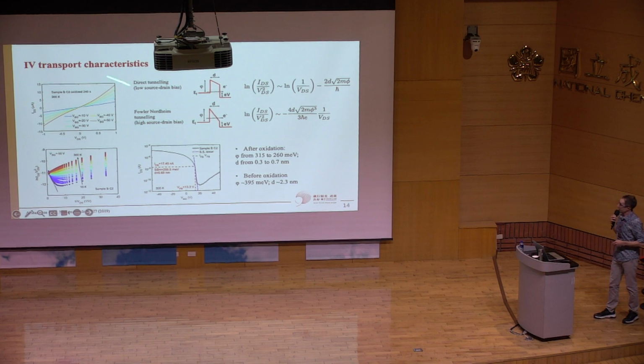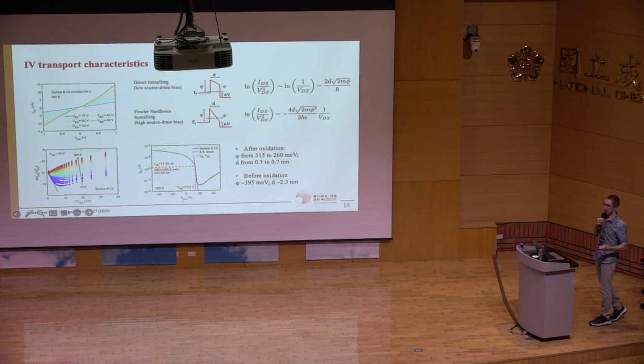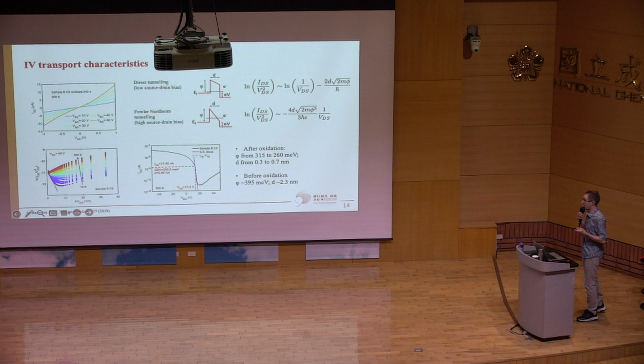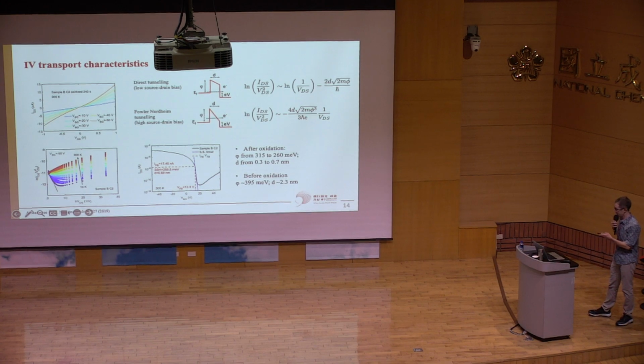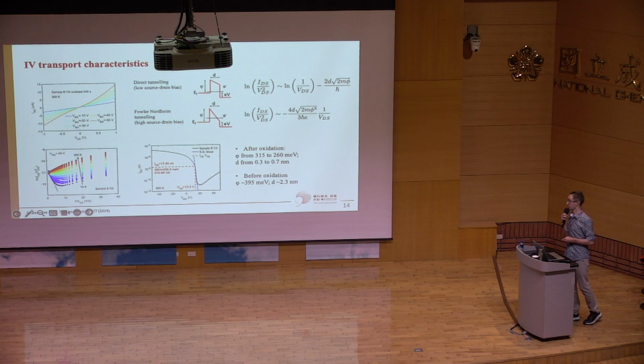Now we found one thing that supports that, really. With our second sample, we just oxidized it for 180 seconds straight away, because we thought perhaps 180 seconds was sufficient to give us a high enough doping concentration. But the IV sweeps turned out not to be so linear. So we exposed it to a further 60 seconds to get this more linear trend. So again, it's supporting this directionality idea in our oxidation process.